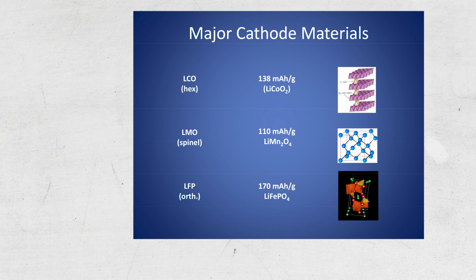But there are some variations, because with lithium cobalt oxide, people consider that cobalt is too expensive, so we have to replace it or substitute it with less expensive materials like nickel, manganese, etc. So now we are talking about NMC materials, but they have basically the same structure, except the slab has, in addition to cobalt, nickel and manganese. Same thing for the lithium manganese spinel. You can substitute parts of the manganese with nickel, and you can also have very high voltage cathode materials based on the nickel manganese spinel. And lithium iron phosphate is the same. The transition metal here, iron, can be replaced by other elements, including manganese, cobalt, nickel and so on. So all of this is actually to improve the performance of the system.